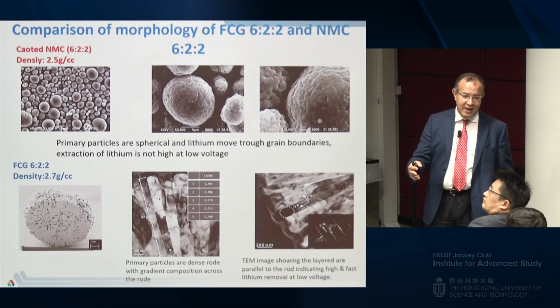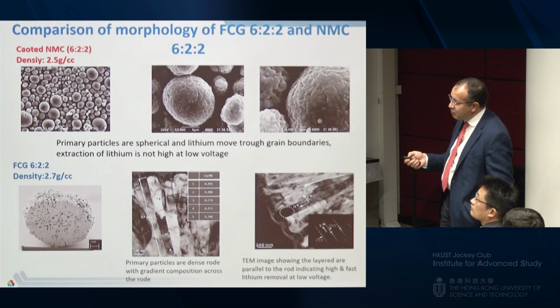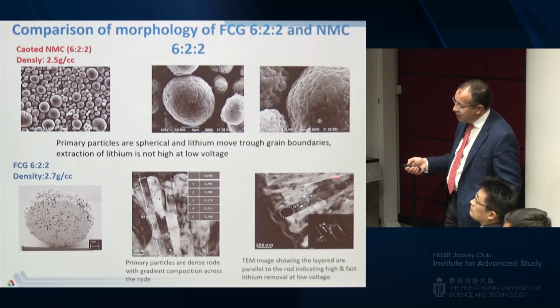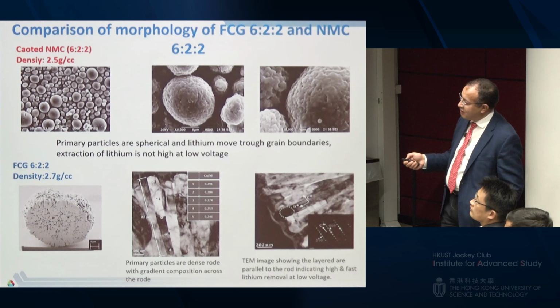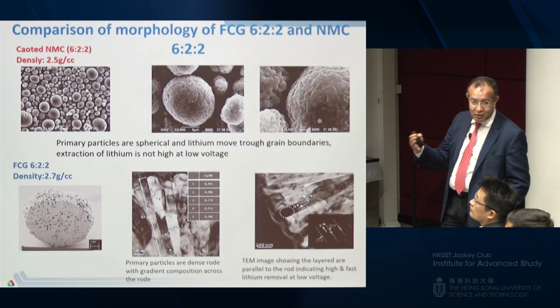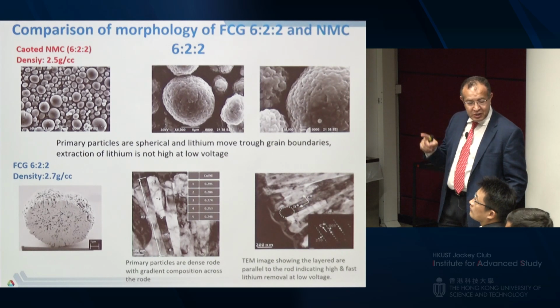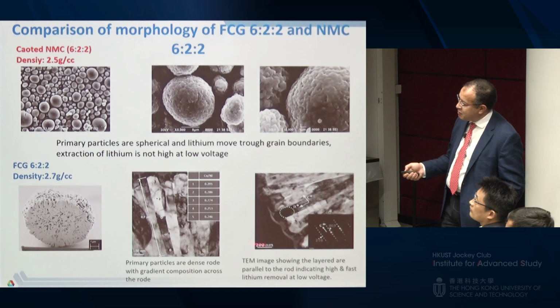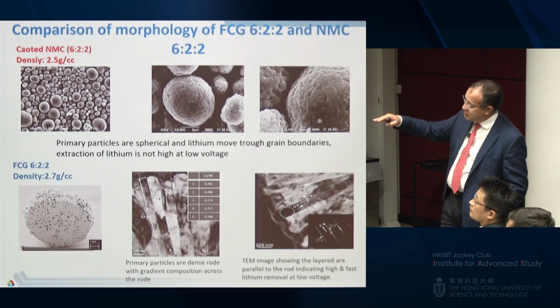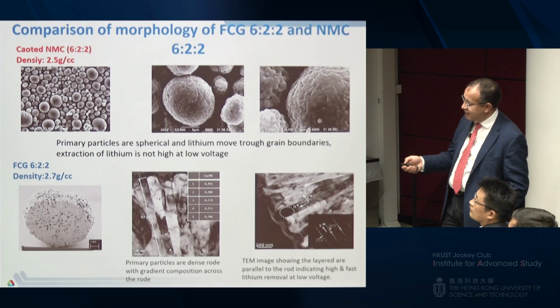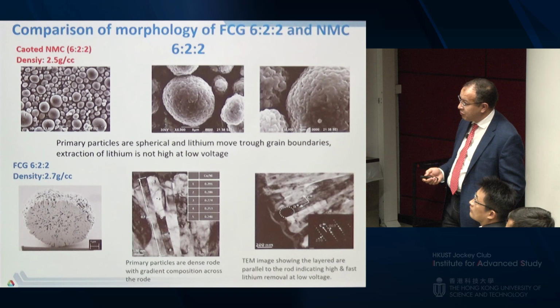So you move lithium faster, which means at the same potential, you may move more lithium here than here, because here the lithium has to go to the grain boundaries, so you don't move as much. Which means the capacity of this material at the same cutoff potential or voltage will be higher here than here. And actually, we've proven that.